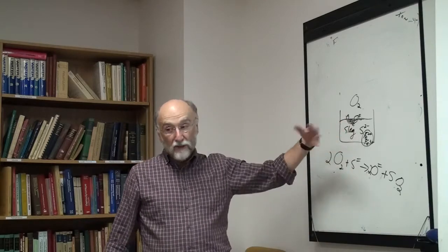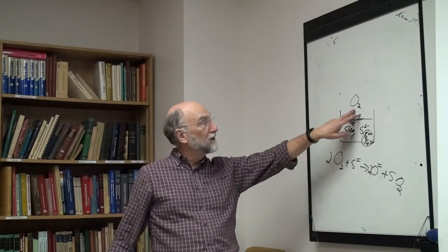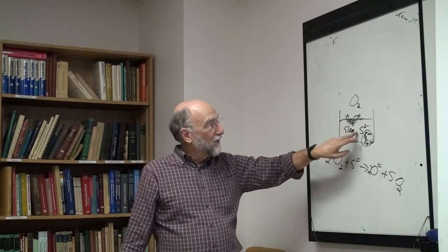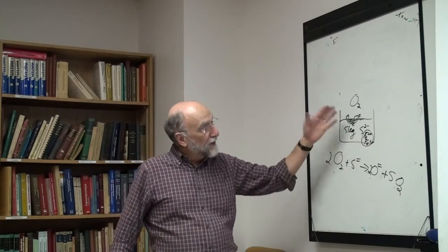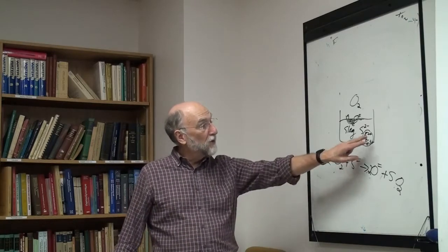So these things can be quite important. There are several steps in a reaction, but it seems that the charge transfer step was the slowest. Somehow the neutral oxygen forming an ion, or the ionic sulfur forming a neutral atom, was the slowest step in the reaction mechanism. Without the iron, the only way to get electron transfer would be for the oxygens and the sulfurs to somehow come in contact with each other and transfer their electrons. I don't know the details, but I certainly know when I added just a pinch of iron to make it an electronic conductor, it was far, far faster.